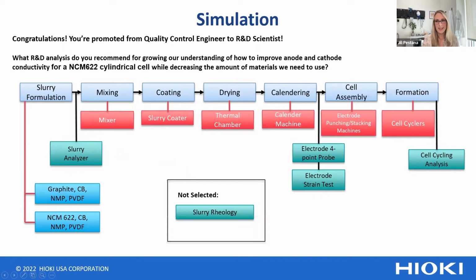So what I would say is to skip the slurry rheology in this case. And the reason for that is, first of all, the slurry analyzer will help understand the conductivity, which is what we're investigating. And then as we move down the line, the 4-point probe will validate, in my opinion, that slurry analyzer result. So we'll understand how the mixing, coating, and drying all come into play. And actually, I kind of messed up this graph. I'm sorry, y'all.